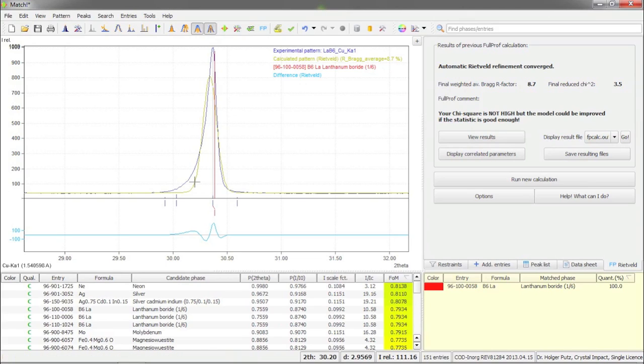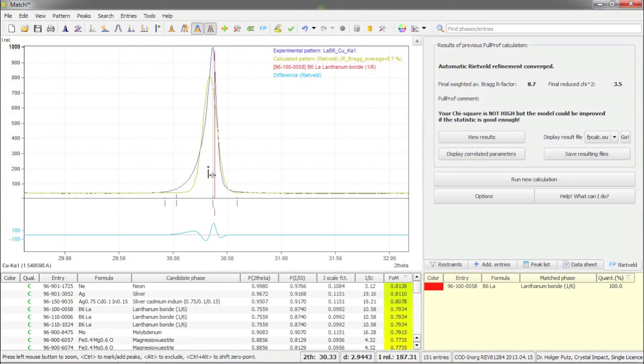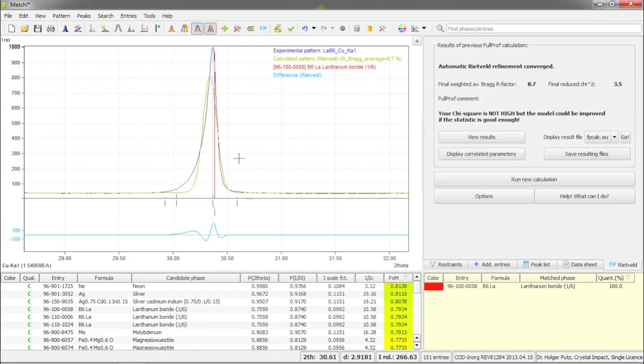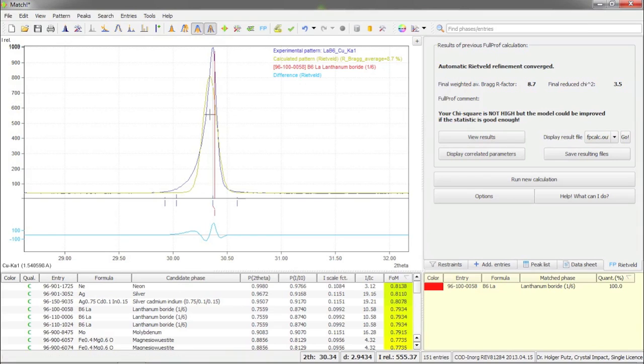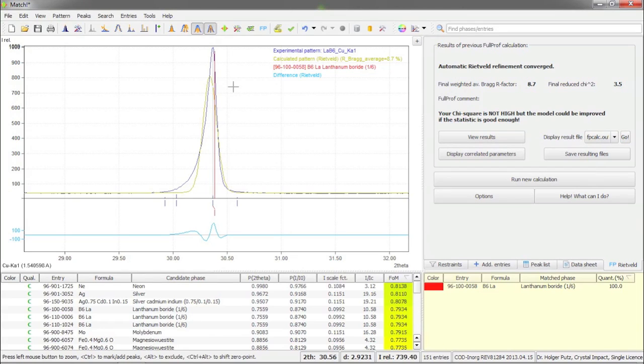As you can see here, the blue curve which is the experimental one shows some kind of asymmetry while the green curve which resulted from the Rietveld refinement does not. The background is simply that a symmetric profile function was used in the Rietveld refinement calculation. We should now run a second Rietveld refinement calculation and use an asymmetric profile function in order to improve the result, and in addition we should also adjust the two theta axis as well as the intensity scaling in order to reduce these deviations.